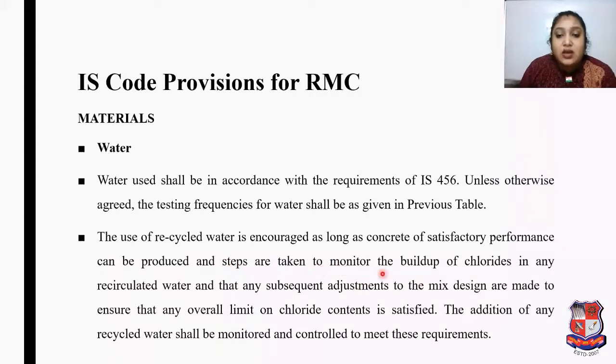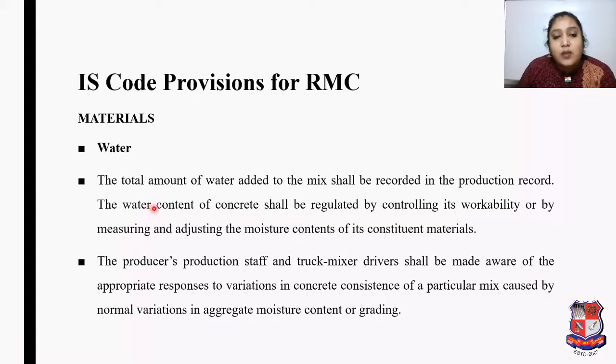taken to monitor the buildup of chlorides in any recirculated water, and that any subsequent adjustment to the mix design is made to ensure that any overall limit on chloride content is satisfied. The addition of any recycled water shall be monitored and controlled to meet these requirements. The total amount of water added to the mix shall be recorded in the production record.